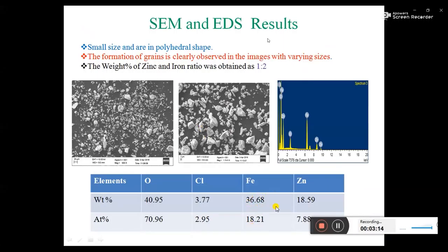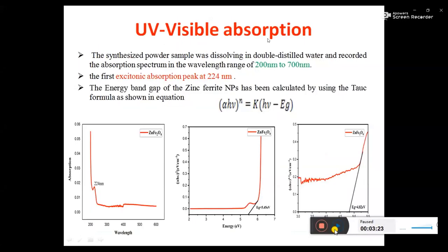And also the EDS spectrum confirmed the formation of zinc ferrite nanoparticles. And also the 1:2 ratio is confirmed as we took during the synthesis of zinc ferrite nanoparticles. UV-visible absorption. The first excitonic peak is observed at 224 nanometer, which is in the UV region. And also we have calculated the band gap using Tauc plot for direct and indirect allowed transitions. For direct allowed transition, the energy gap is 5.45 electron volt, and for indirect, 4.82 electron volt. This wide band gap suggests these nanoparticles can be used in photodegradation applications.